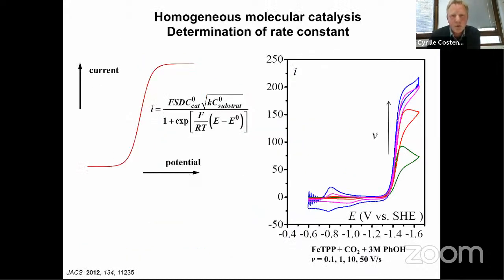So let me just show you very quickly a real example. Here is the situation of a system that I will describe in more detail later on: the reduction of CO2 using iron TPP porphyrin as a catalyst in the presence of a high concentration of proton donor. At low scan rate, you get a peak CV here because you get inhibition of the electrode, because you produce CO, which is an inhibitor of the electrode surface.